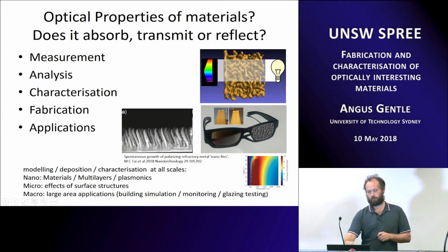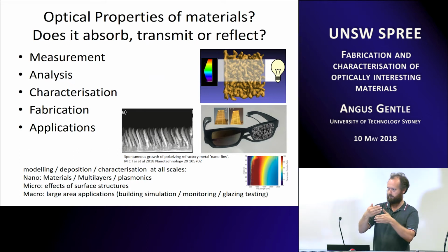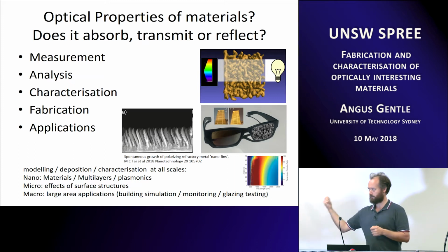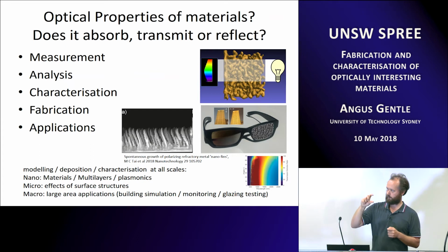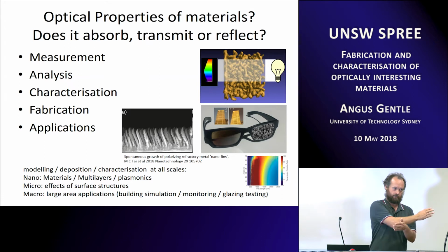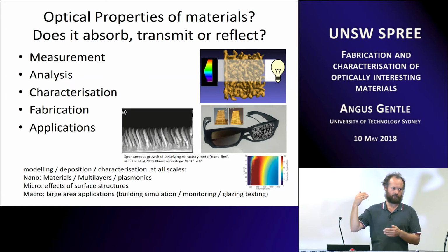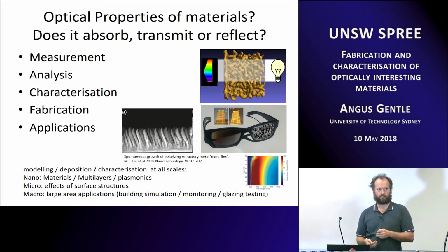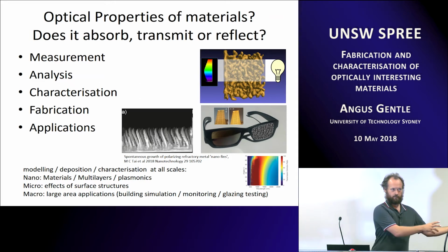So this one here was from a paper where we were de-alloying. So we do some gold sponges. You start with a gold aluminium sponge, alloy, so AuAl2, it's purple gold. You put it in sodium hydroxide and it de-alloys into a really porous, nanoporous sponge. And so people had always wondered, how fast does it actually etch? So some groups had done it and you etch it for a little bit, take it out, do TEM and go through. We put it in a little cuvette with a spectrometer on it and then measured the spectrum every second as it etches out over however long, and then did the optical fitting of it so you could actually work out the etch rates. So it's a way of doing in situ analysis of a material.